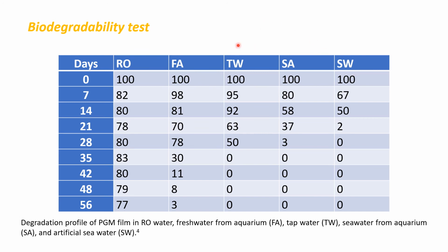The table features the degradation profile of PGM films up to 56 days. It is revealed that the PGM film degrades faster in waters with higher salinity, which accelerates degradation, as we can see from the results of SA and SW. PGM film from modified prepolymer is predicted to have the same behavior, but because of the ester bonds present in its molecule, it will be slightly lower than PGM film from unmodified PGM prepolymer.